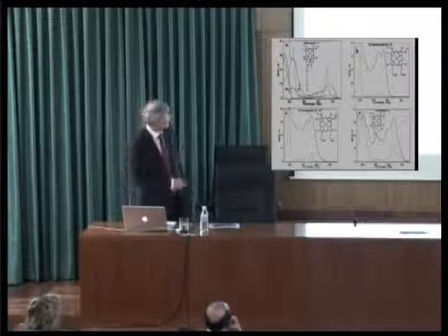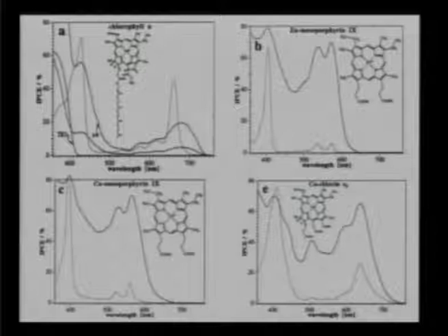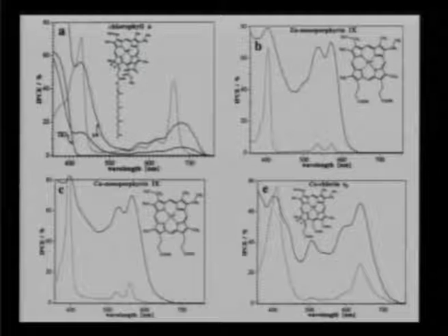And so we also used natural dyes. I skip over this. We were interested in using green dyes from nature, so we can use chlorophyll. We don't get that much, because there's no attaching group. You see, it's important to have those anchoring groups, the carboxylates. They bind to the titanium ions on the surface by coordinated binding.